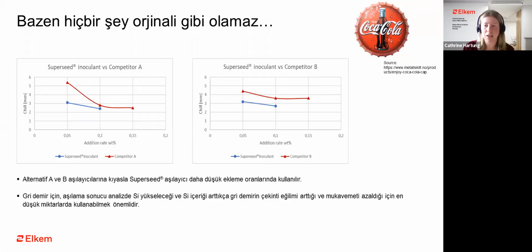So this was a very successful product when it was launched, and we today see a lot of different strontium containing inoculants from a lot of different suppliers. So Elkem did a benchmark study on this. We collected different Superseed copies or Superseed alternatives from all around the world. And we did a trial in-house in our lab using hypo-eutectic iron, so similar to what you saw in the previous case, the low carbon equivalent. We tested then all the different inoculants that we could get hold of against our Superseed.